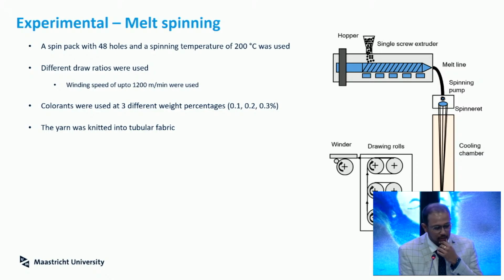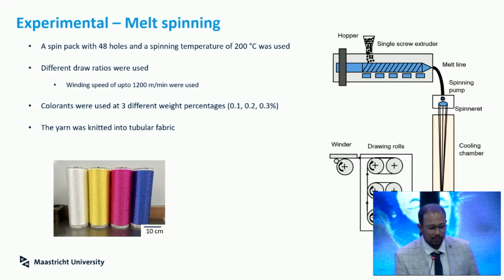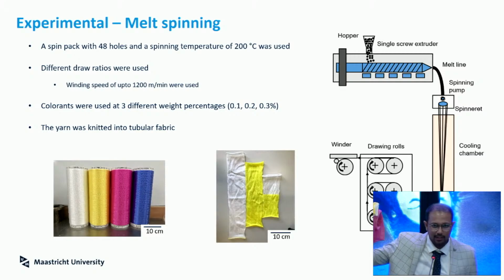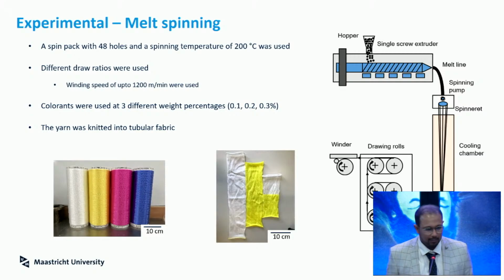Then, with the colorants that performed well, I went into the spinning process to make a melt spun yarn on a pilot scale or semi-industrial scale. I used 3 different weight percentages of colorants to do melt spinning. As you can see in the picture on the right side, during melt spinning we typically have an extruder to heat the polymer, which is molten, and then pull it down to make yarn. Depending on how fast we draw the yarn, we get different properties, different crystallinity, and so on. Based on this, I got some different materials, which were also knitted, as you can see here, into fabrics.